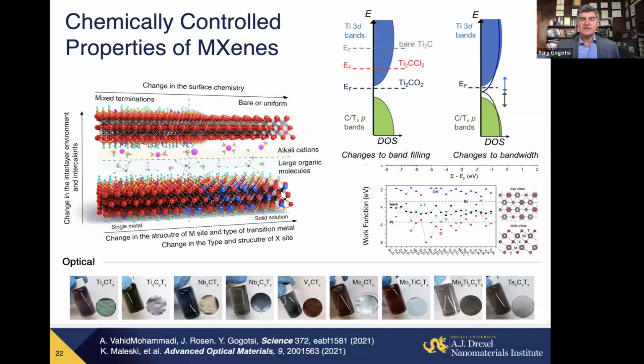When we do synthesis of materials, we can select different elements and mix them in the necessary proportion. We can modify the surface. We can even intercalate ions or connect organic molecules by covalent, electrostatic, or van der Waals bonds and tune the properties. Just a very simple example. Work function, the ability of materials to emit electrons, is very important in, say, optoelectronics, solar batteries, lighting. It changes from 2 to 6 electron volts when we replace hydroxyl groups with oxygen on the surface. And we actually can do it electrochemically.